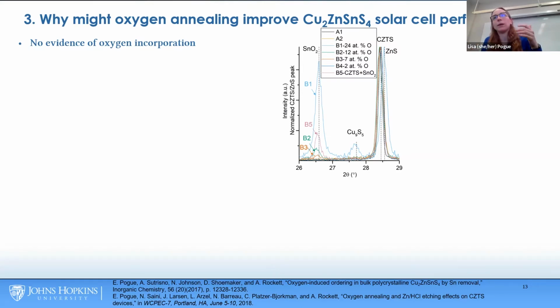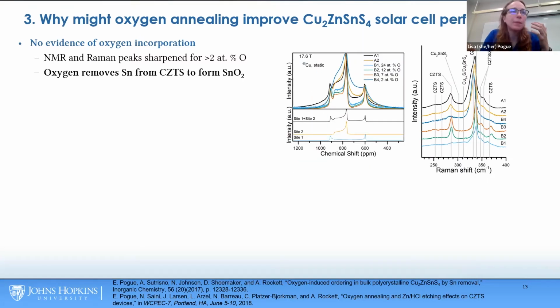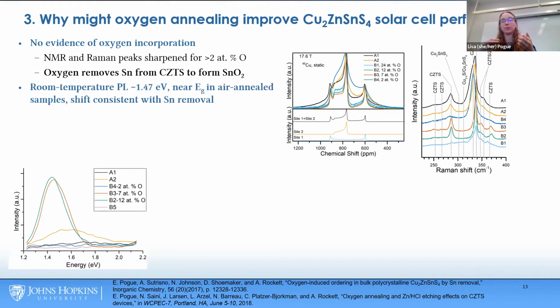I looked at how this might be happening and found that oxygen is not incorporating in the CZTS, but rather it removes residual tin. The residual tin seems to promote disorder in the kesterite structure that is harmful for eventual device performance. And so when you do the air anneal, it reduces that disorder, but it also creates some tin oxide and